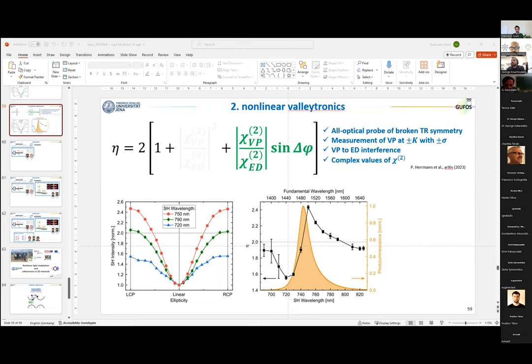The other thing that I should mention is that this shape depends on the interference between the valley polarization and the intrinsic response. So while for the intrinsic response, we can look at the absorption and we can somehow estimate what we would expect, for the time reversal symmetry, we don't have any benchmark, no?